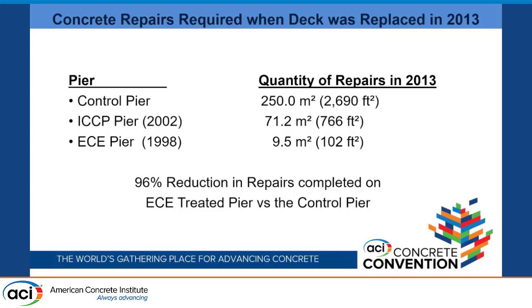And you can see the effect again in terms of the reduction in the amount of cumulative concrete damage. So from the repairs that were done in 1998 until 2013, when they did the next round of repairs, there's a big difference here between the amount of additional repairs that were required on the pier that had chloride extraction compared to the control pier, which just had concrete repairs and no other things done.